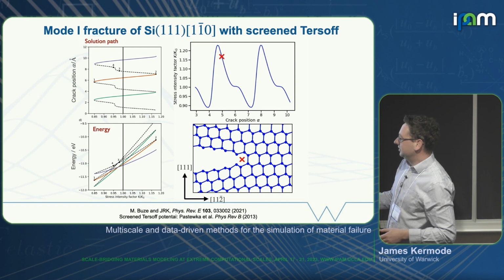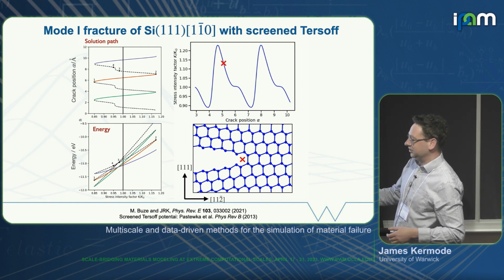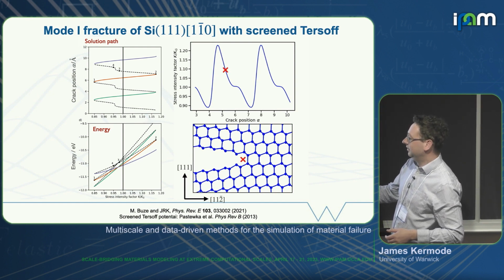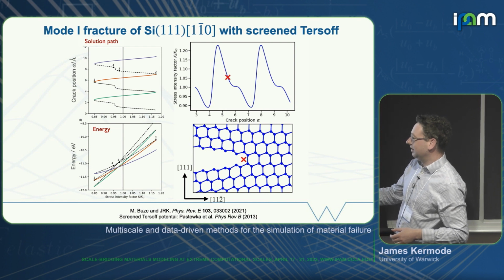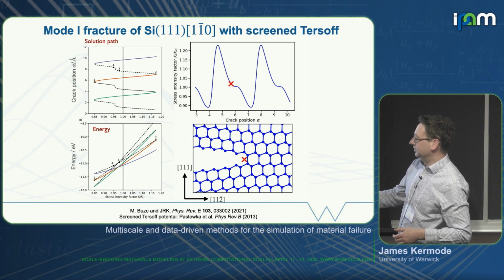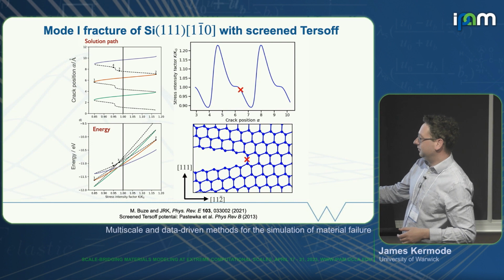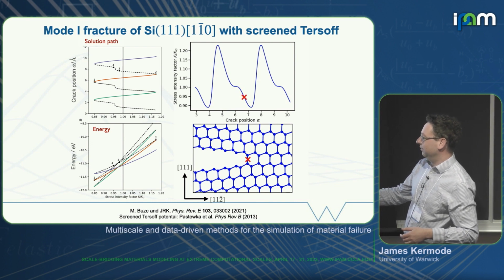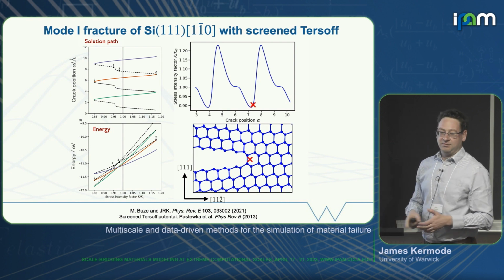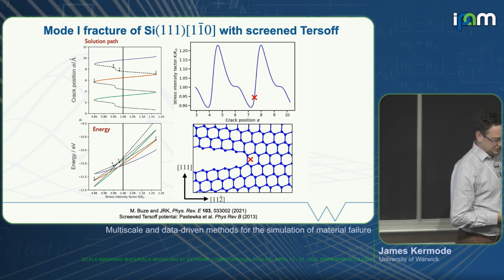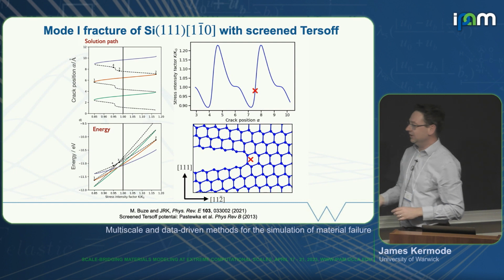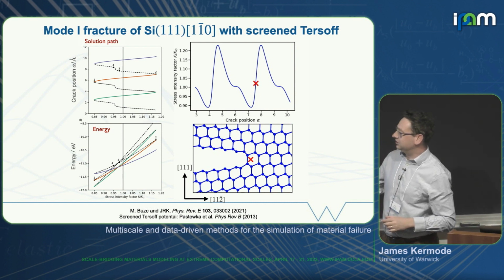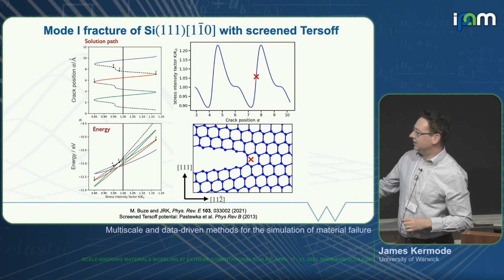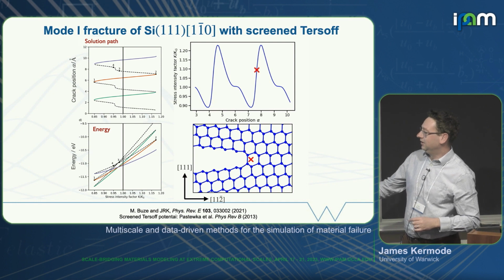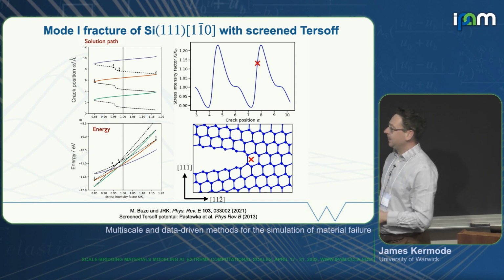Under standard conditions of a fixed stress intensity factor, fracture would correspond to jumping vertically in this diagram. So you'd move forward in crack position at fixed K, and you'd have to pass through a transition state here to get from one minima to the next one. So the dashed part of the diagram maps out the unstable parts of the solution path. And the nice thing about the numerical continuation is that it can follow round the folds in the bifurcation diagram and continue to find equilibria that are saddle points as well as minima.